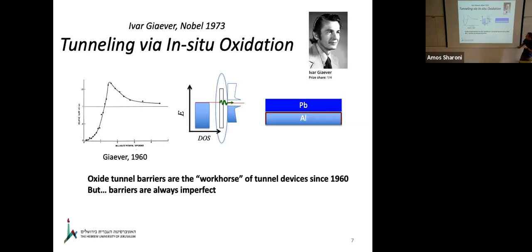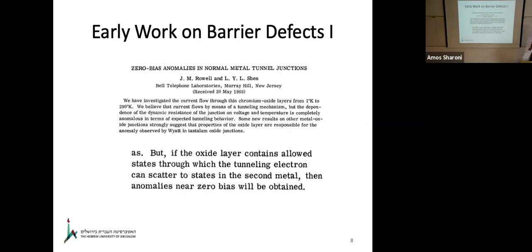Now, these tunnel barriers, these oxide-based tunnel barriers are a real workhorse. Till this day, almost everybody does quantum information based on superconductors, and you have labs like that all around now. They use the same aluminum oxide tunnel barrier technique. And if you want to isolate small regions like a quantum dot, you also use the same technique. And that's what I'm going to show you next, because Giaever invented this technique in the late 1950s.